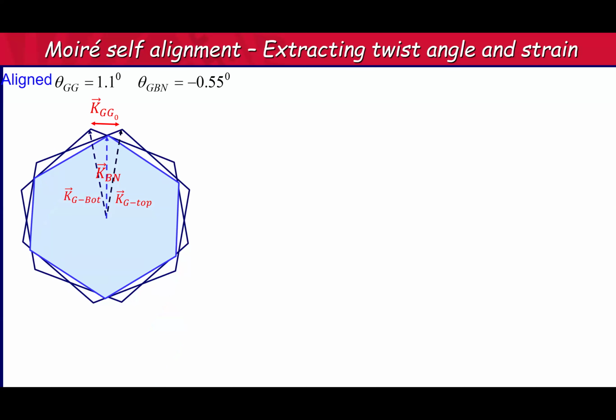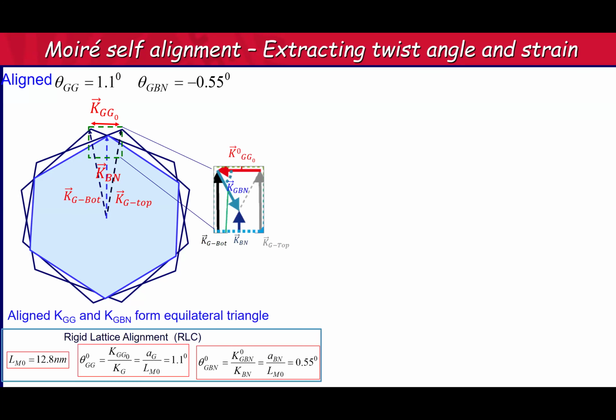When I zoom into the reciprocal lattice, because the twist angle is very small, these reciprocal lattice vectors are kind of straight for the graphene, and this is the boron nitride one, and of course they're different because the lattice spacing is different. Alignment means that there's a 60-degree angle. You have an equilateral triangle here. That's what alignment means. So the K at 0 means unstrained. KGG naught is equal to KGBN in magnitude. Once you know that, you can calculate what the twist angle is. You can calculate theta GG, theta GBN. You can calculate the relaxed Moire wavelength, 12.8 nanometers for 1.1 degrees.